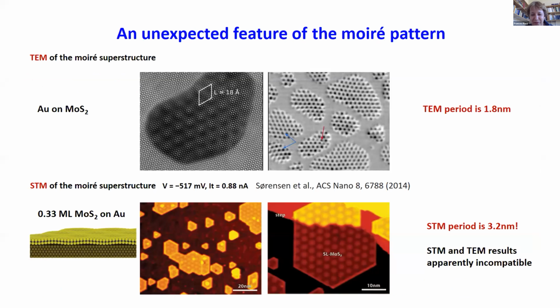Well, the first thing we could do is measure the spacing of the moiré pattern, and we already run into some trouble here because we get 1.8 nanometers in TEM between these spots. But when people do STM and they measure the electronic structure, they get a different period for the moiré pattern. So what is possibly going on with this?